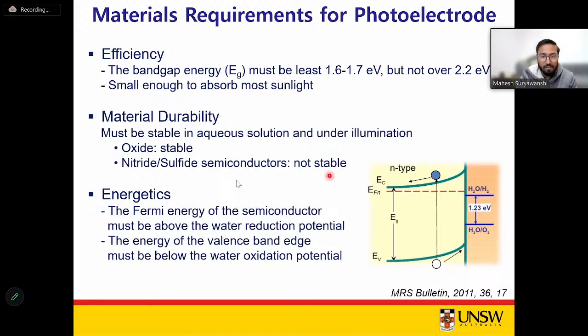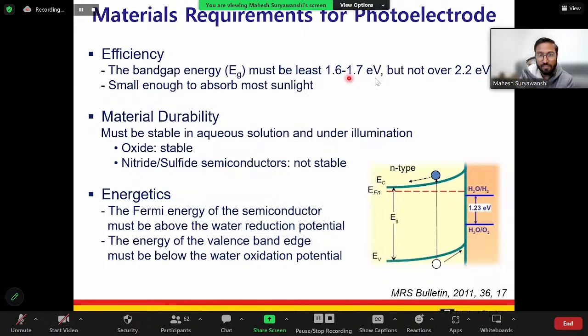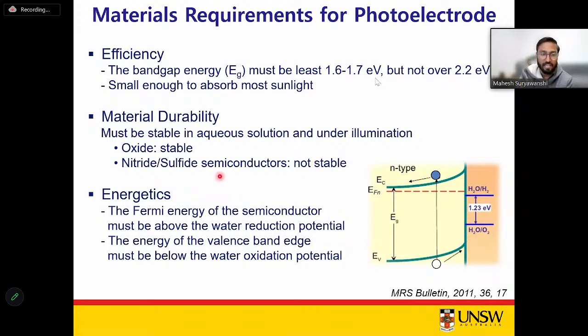So my point is that we have materials available in the literature, but there is a trade-off between these materials' performances. One material is stable in the aqueous electrolyte, but its band gap is not great enough to absorb the maximum of sunlight. However, other materials have a suitable optical band gap energy to absorb the maximum of sunlight, but they are not stable. So this is the research gap in this current field, and this is where we need to work on. We need to find suitable materials that possess an optical band gap energy in this range, but are simultaneously stable in aqueous electrolytes, and that's what we are trying to do, or have done so far, which I will show you in my next few slides.